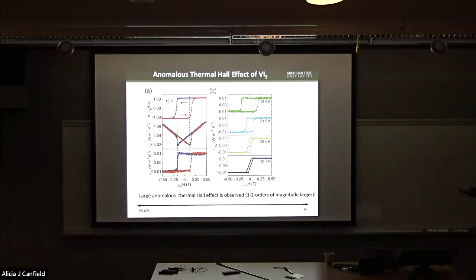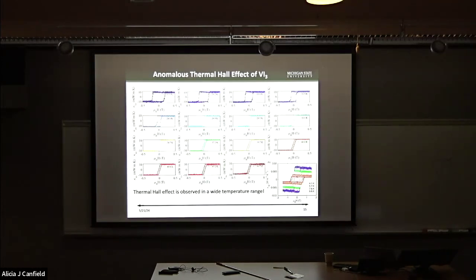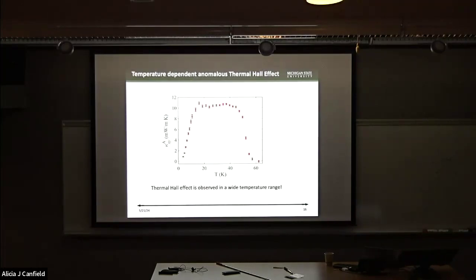And second is that at zero magnetic field, the thermal Hall signal is still very large. It's almost the same as the saturated value at 0.5 Tesla in this case. So this tells us that in our system, we have an anomalous thermal Hall effect. Here we measure the thermal Hall signal over a wide range of temperature, from 4.7 Kelvin all the way to a temperature close to the transition temperature. From here, we could extract the temperature dependence of the anomalous component of the thermal Hall signal. And this is what we got.